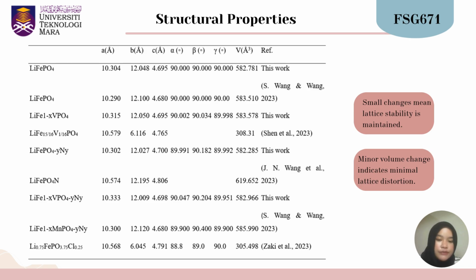For the sample doped with vanadium and nitrogen, the change in lattice parameters is very small. This indicates that the lattice stability is well maintained despite the doping. Additionally, the unit cell volume changed minimally from 582.781 Angstrom cubed in the pure LiFePO4 to 582.966 in the doped sample. Such a minor volume change suggests minimal lattice distortion. Maintaining such small distortion is important because it helps preserve the material's crystal structure, which is essential for stable battery performance.